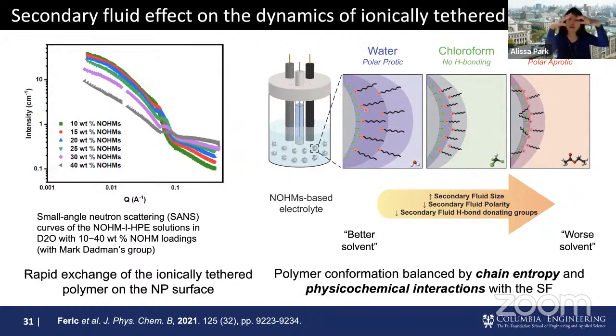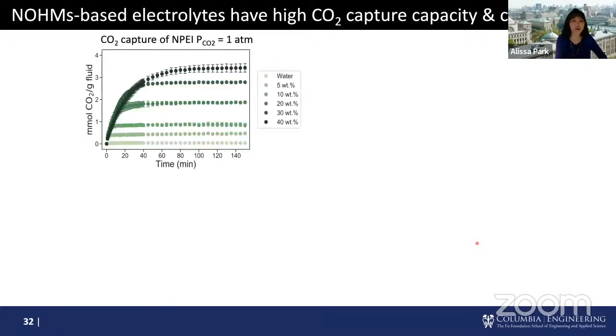And those are kind of a pseudo system of NOHMs, so the overall size of the polymer, the NOHMs, and how the NOHMs interact with the secondary fluid, ionic species and even CO2 was highly dependent on how the interacting polymer and tethered polymer are interacting with them. So it was very interesting looking at this. Because of that, now we had to look at, once we bubble CO2, how much CO2 we can load into this NOHMs-based electrolyte.